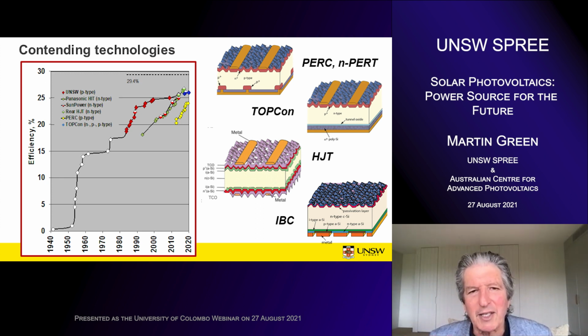And the limit is about 29%. So that's the best you can ever do. So we're getting quite close to those limits. But since 2015, there's been 4 technologies that have now also exceeded 25%. We were the only ones for a long period, but not only is there our PERC structure, which, as I mentioned, is the industry standard, but other structures that are shown there.